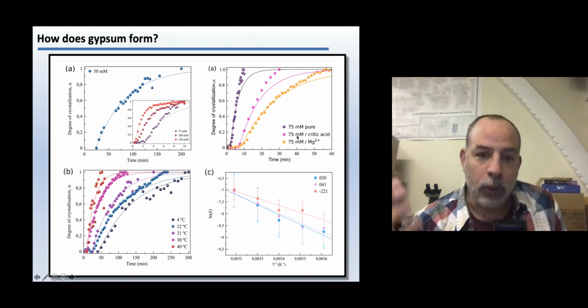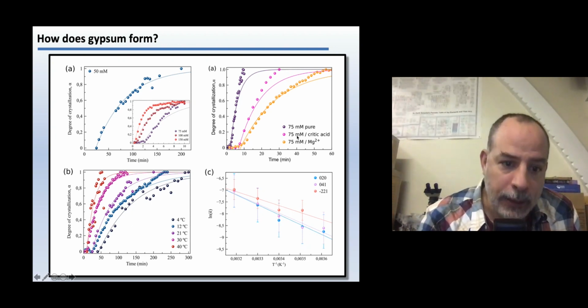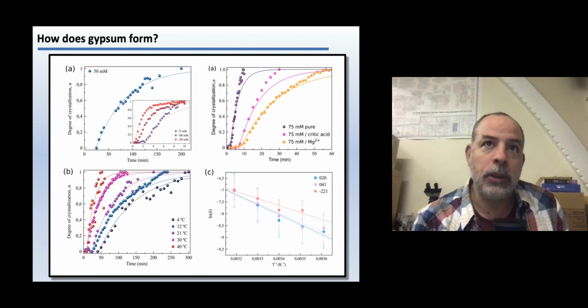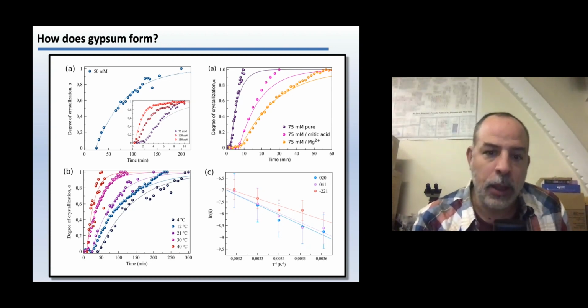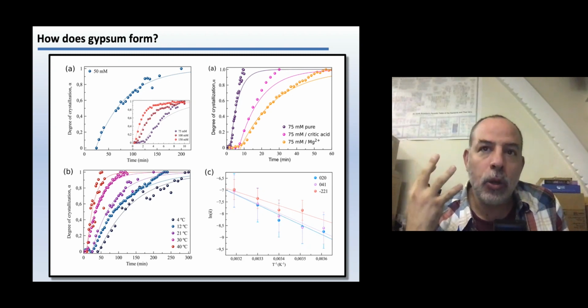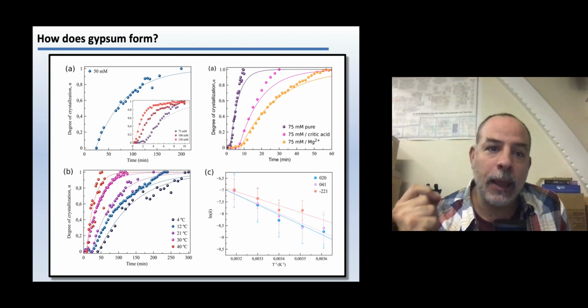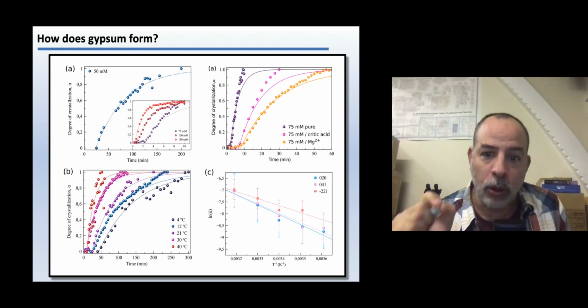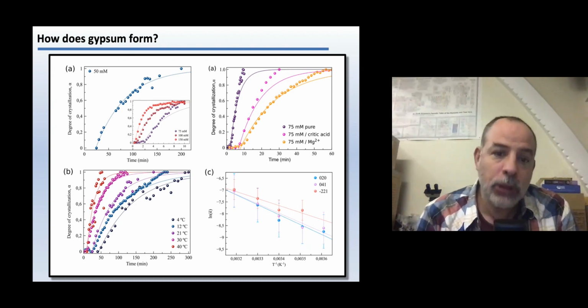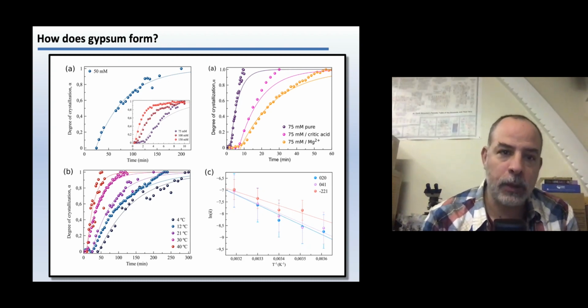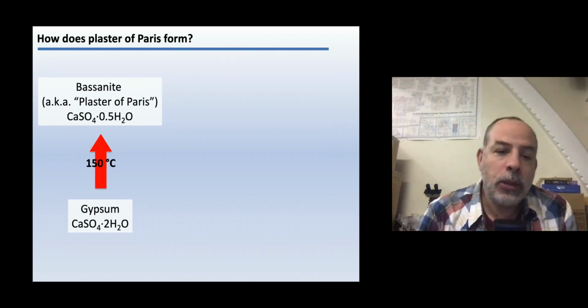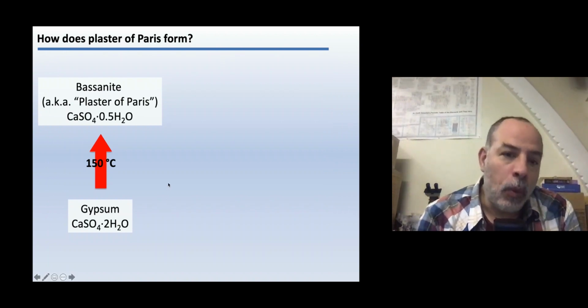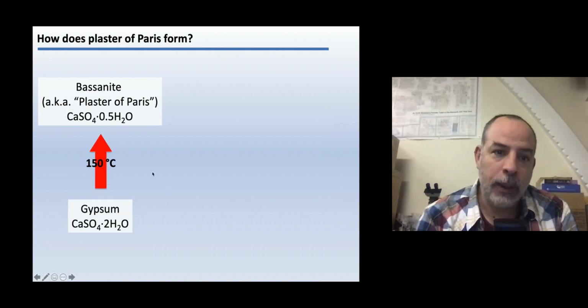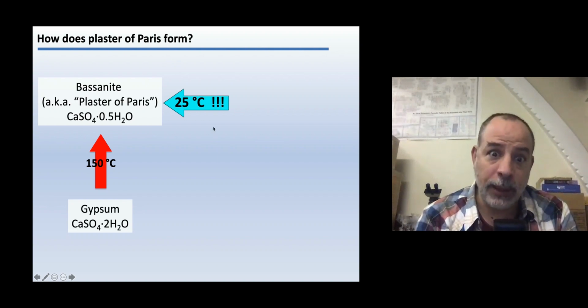And from here, what we can get is the kinetics of the crystallization, of nucleation, and also the energetics of the reactions. Okay, so this shows how useful synchrotron-based techniques can be to follow crystallization reactions. Otherwise, it will be essentially impossible to obtain so good data. Okay, so what we saw is that yes, we know that gypsum can be transformed into bassanite at 150 degrees C, but bassanite can form at ambient temperature, and that will be amazing.